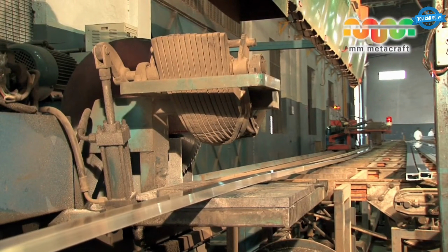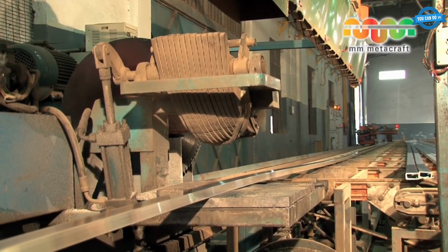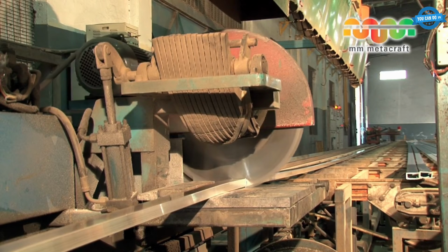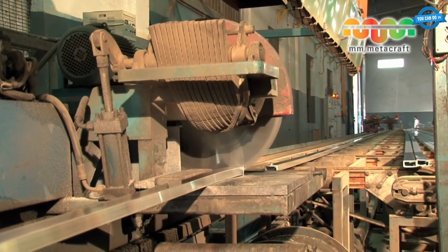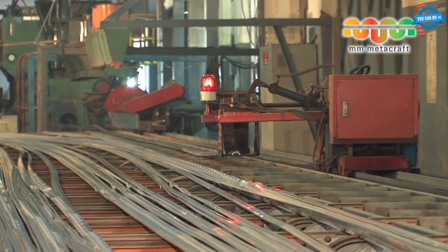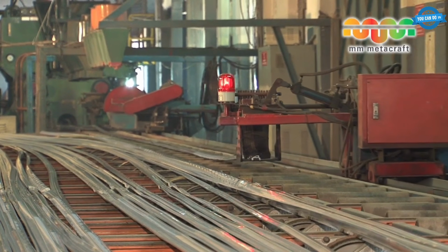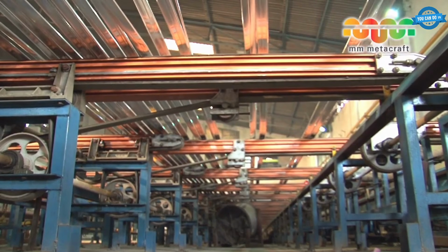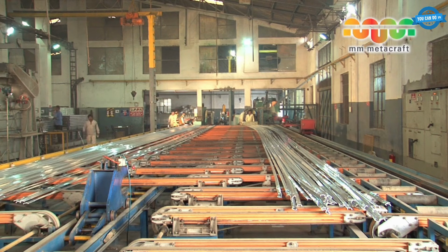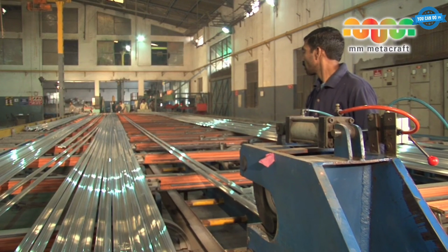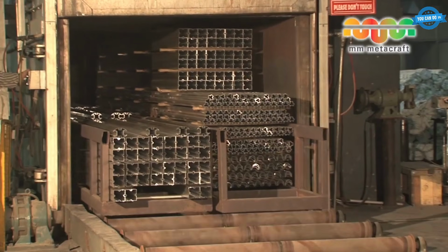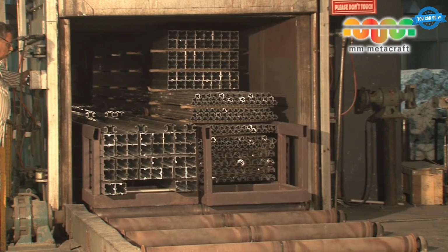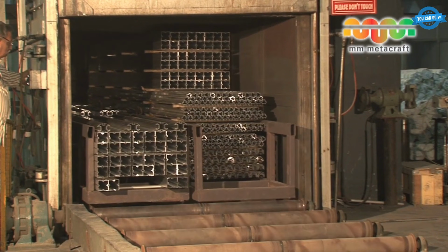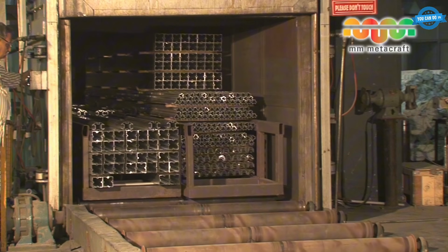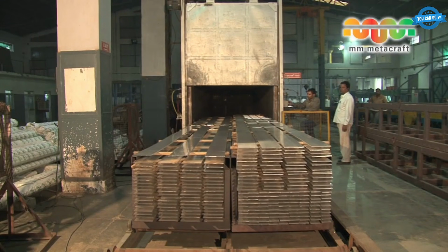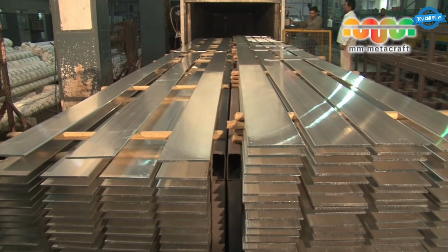Why does it work? At 450 degrees Celsius, aluminum behaves like stiff toothpaste. Push it through a shaped opening and it flows. Cool it back down and it locks into shape with full structural strength. Cooling immediately downstream uses air or water. Stretching removes residual stress. Cutting to length follows. Aging ovens then build in the final hardness. Anodizing or powder coating finishes the surface. The plant runs 4,500 metric tons per year.